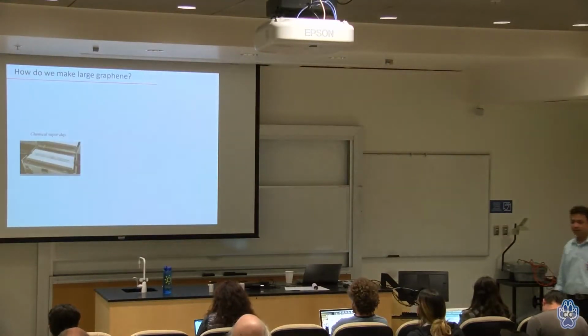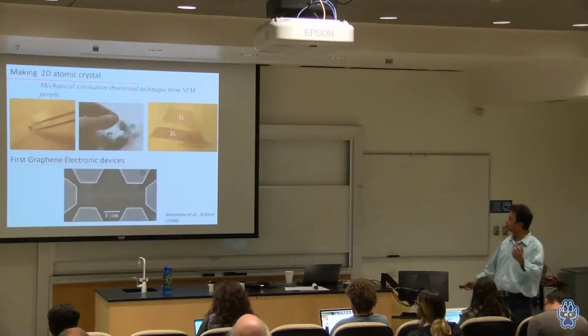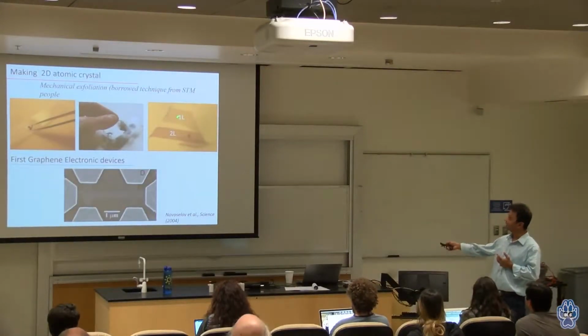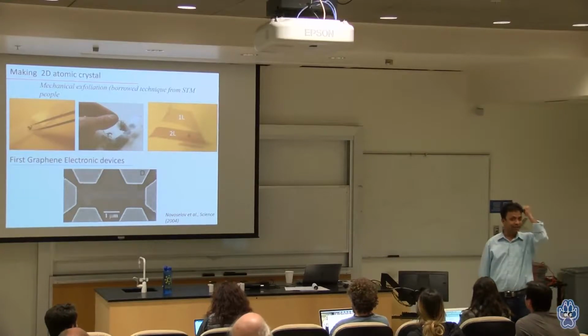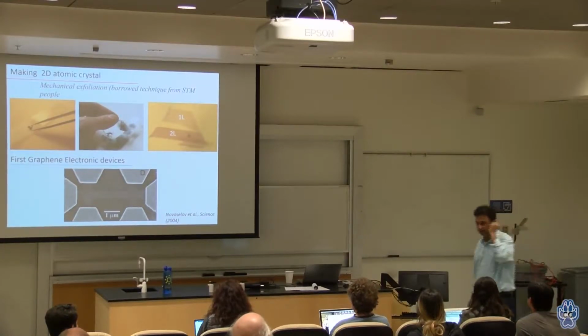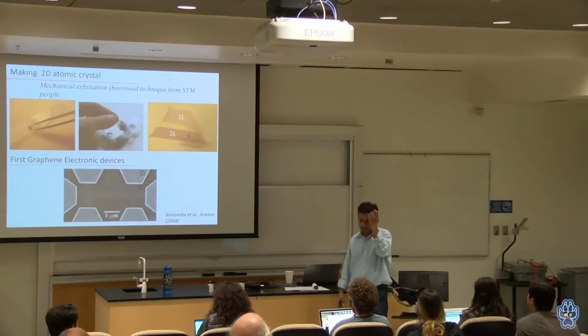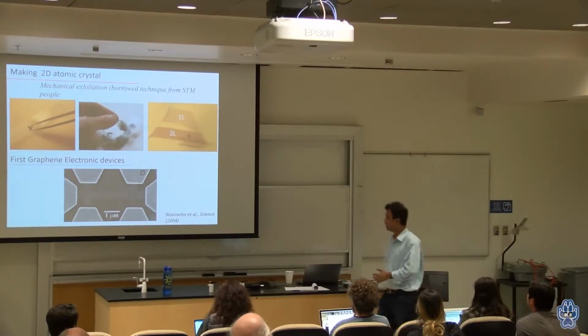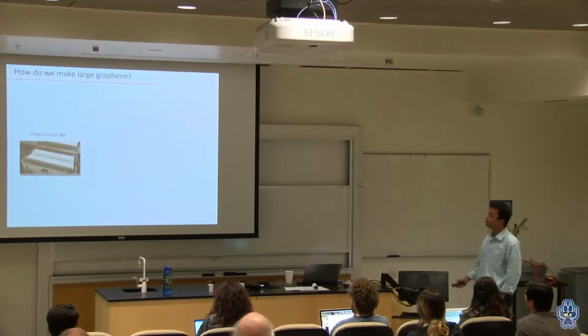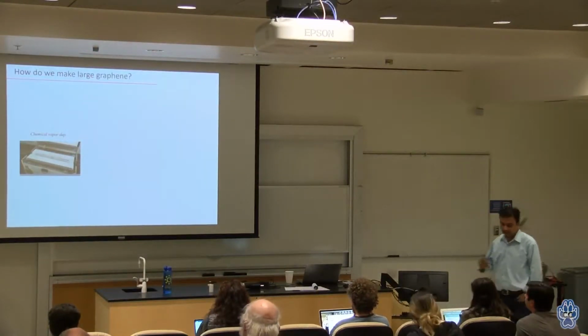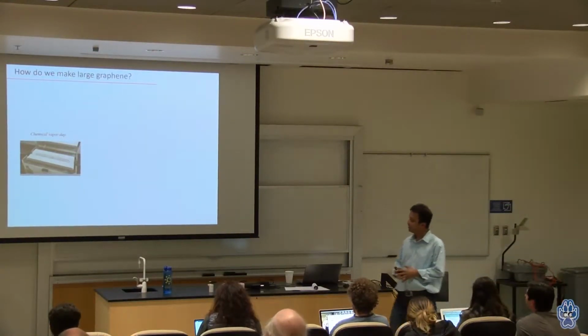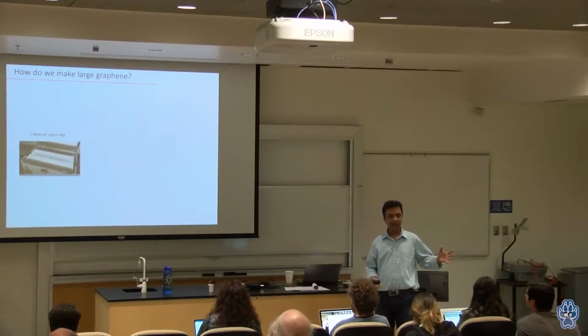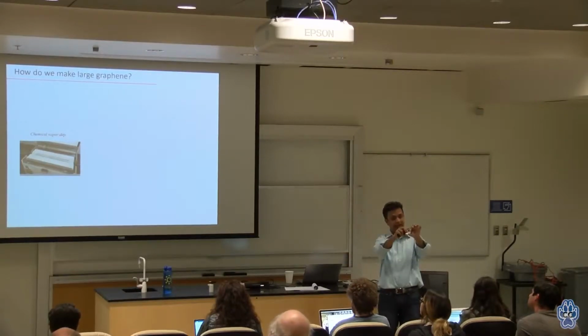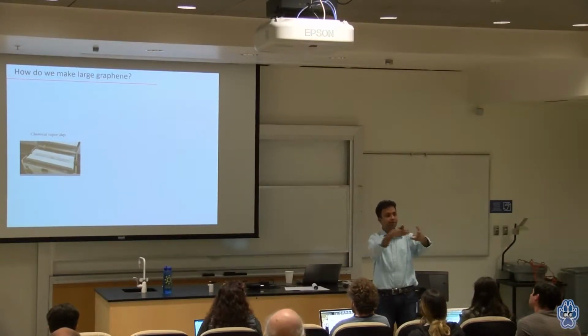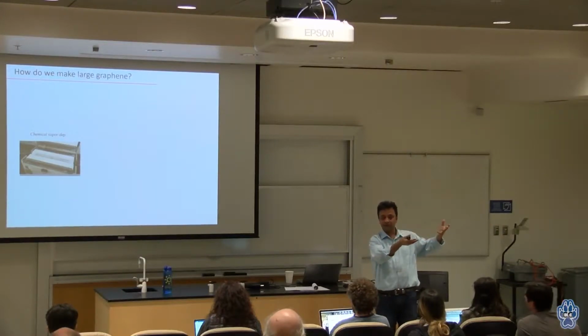Now you can ask me, well, the materials in the Scotch tape, this scale is 5 micron. What is 5 micron? Less than your hair thickness, right? That is not feasible for application purposes. So people have developed a recipe so that now you can make really large scale, and they call it a chemical vapor deposition system. They have a furnace and a vacuum system, and they put some metal, for example, a copper foil.